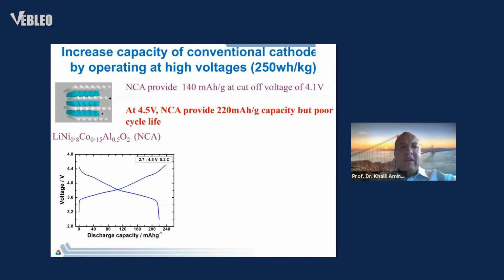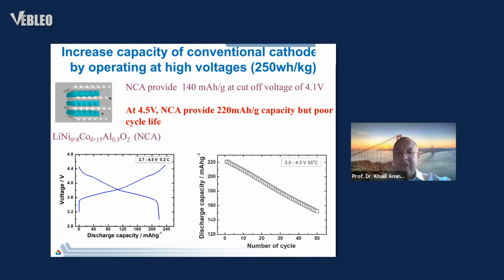Now, if you take, for example, the lithium nickel cobalt aluminum oxide, that's the NCA, it is very popular. Tesla pioneered this material for their batteries. If you operate at 4.2 volt or 4.3 volt, you can get some very good cycle life out of the system. However, if you go higher in voltage, 4.5, 4.6, you get very high capacity, up to 240, but the cyclability drops very quickly. So the material doesn't cycle well.